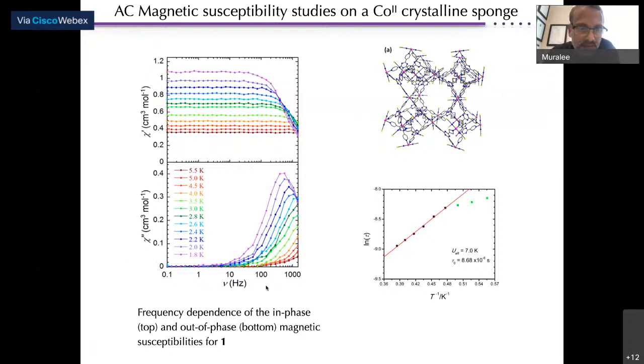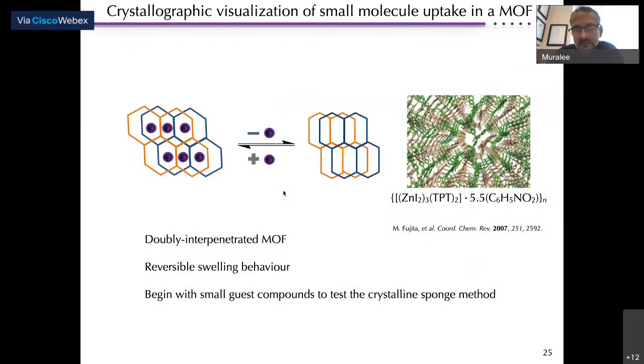This is the out of phase susceptibility as a function of frequency, and this is the in phase. And these frequency dependent signals clearly indicate that you have a magnet-like behavior for this MOF, where the magnet-like behavior is arising from a single unit of this cobalt ion, which are barely connected in terms of magnetically speaking. These are not communicating, but the magnetism is arising from each individual cobalt center. So this is a potential use in the future if we can create magnetic MOFs. Perhaps magnetic separation is also an avenue that we can explore.